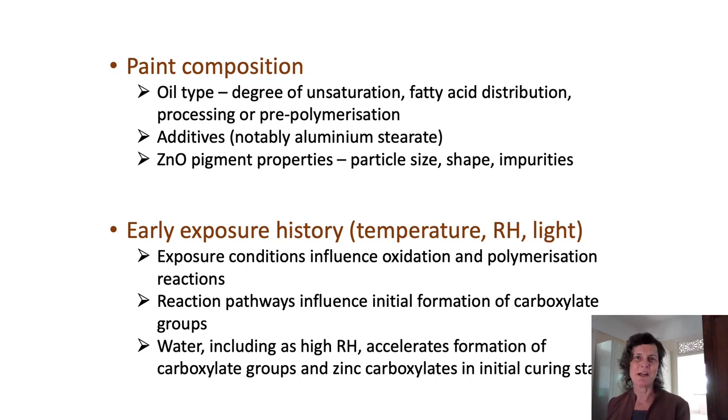So what are the conditions that might encourage soap crystallization in paintings? There are factors both within and beyond our control. Paint composition is something we have to live with once a painting has been created, and the type of drying oil, paint additives such as aluminium stearate, and pigment grade in the paint will all influence soap formation. There is increasing evidence too that the early environmental exposure history of a painting affects initiation and formation of carboxylate groups and consequently zinc carboxylates as the paint cures and polymerizes. Elevated relative humidity is understood to be particularly significant in accelerating formation of carboxylate groups during auto-oxidation of the oil medium.